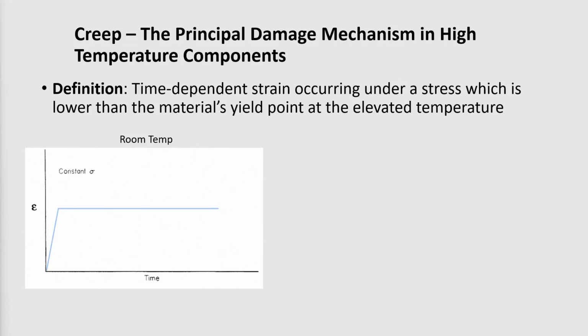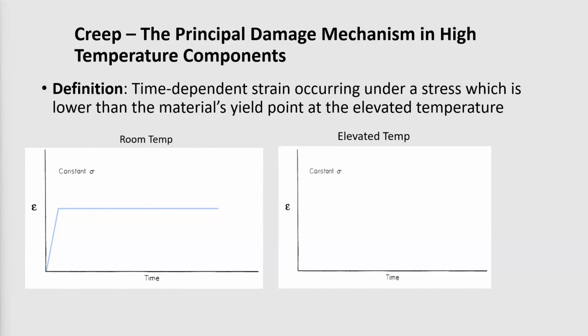And if you hold the stress at that particular level, that strain will be maintained at that same level regardless of how long you apply the stress. So unless you increase the stress, there will be no increase in the strain. Creep, however, is a different matter because it is the time-dependent strain that accumulates at a particular temperature and at a stress that's below the yield point of the material, or that can be below the yield point of the material at that temperature.